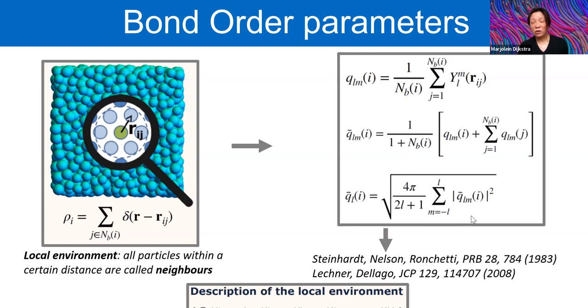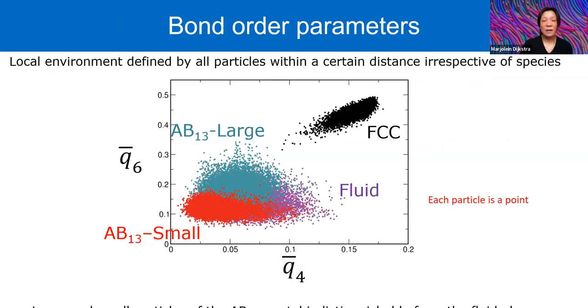You can take the cubic or the quadratic variant of it, and then sum over all the m values to make it rotationally invariant. You can calculate all these Ql values from 1 all the way up to 24 or 12. They basically measure the symmetry of the particle with its local environment. Often Q4 and Q6 are used for crystal structures because of the 4-fold and the 6-fold symmetry of most crystals. However, if you do that for the AB13 crystal structure, then we immediately see that